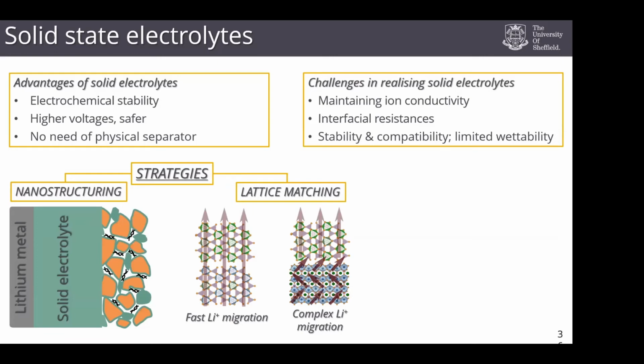You might have, for example, a sort of lattice mismatch where lithium ions are quite happy moving through this material, but once they reach this one, not so happy, they've got to move around it. So if we can engineer materials that are compatible with each other, not just in terms of their chemical stability, but also in terms of the resistance to ion movement across interfaces, then you could potentially look at a device where the ion mobility is sufficient that you can have an all-solid state battery.